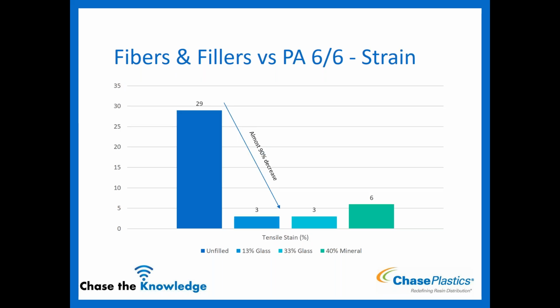And then you take a hit here. If it's something where your elongation is important and it needs to be able to elongate just a little bit, you're going to start to lose that as soon as you add fiber. So just keep that in mind. It takes a huge dip, like a 90% decrease in nylon itself. You still get quite the decrease in your mineral, not as great.